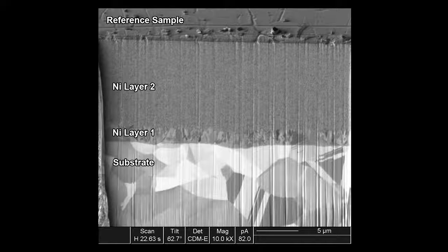This is a really interesting example. This is a decorative plating on a brass substrate, and it has two different types of nickel layers, and so they have different grain structures in them because they were done in different ways. Now, the lower nickel layer has a coarser grain structure. The upper one has a much finer grain structure. And this is done intentionally during the process in which the platings are put down.